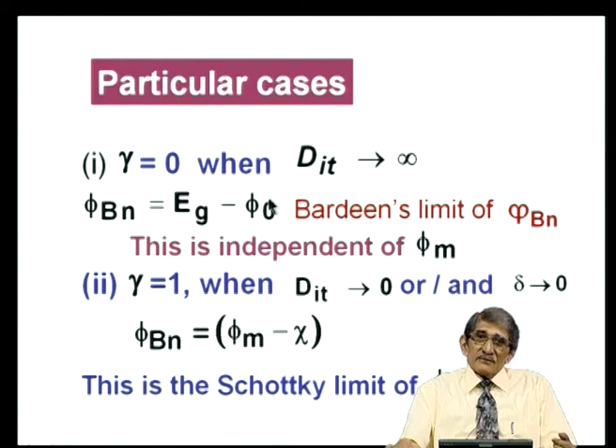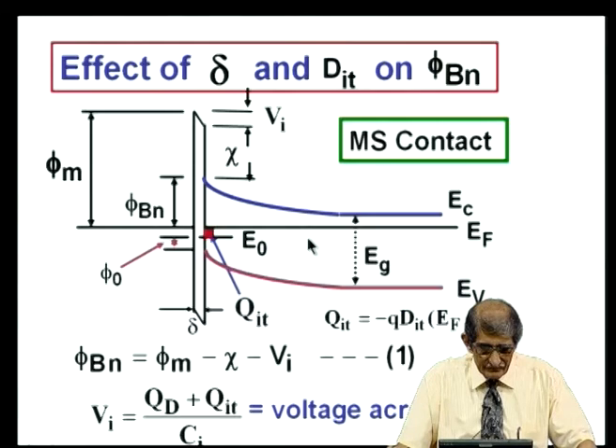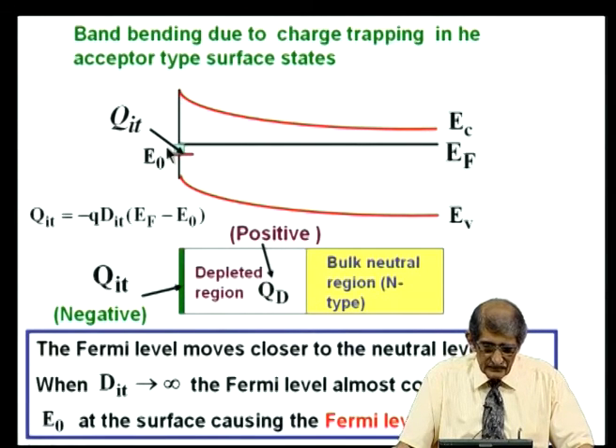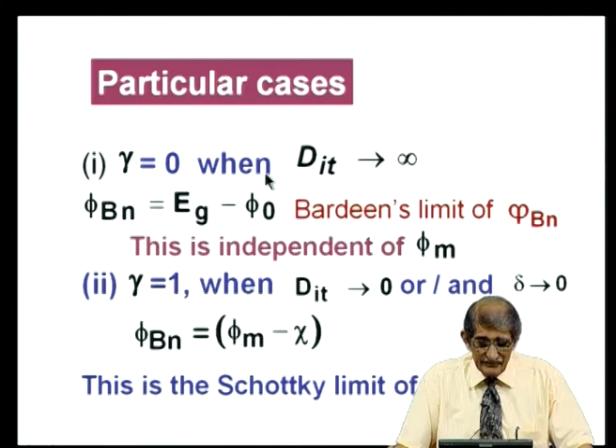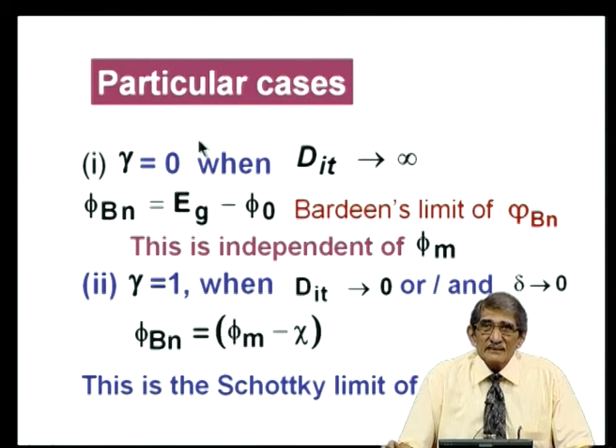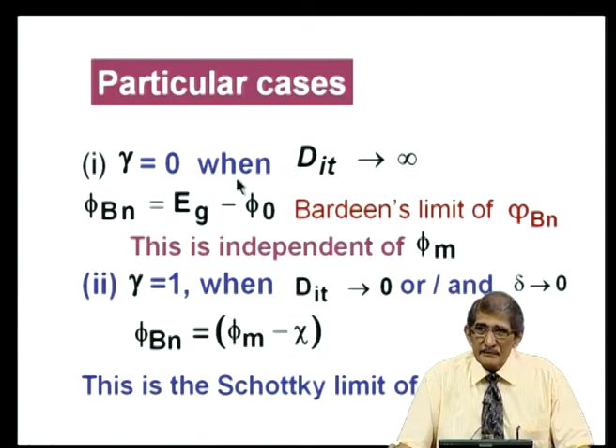So, if you get rectifying in the case of n type material, what if you make it on p type material? Again, Fermi level pinning will be there. What will be the barrier height phi_bp? Supposing this is 2/3 of E_g, for the p type material, the barrier height for holes will be E_g minus that. That is the barrier height for electrons, and this is the barrier height for holes. So, if this is 2/3 E_g, that is 1/3 E_g. So, the barrier height for holes will be smaller. So, it will be easier to make p channel devices with metal semiconductor contact, because it makes ohmic contact with holes, or p channel.